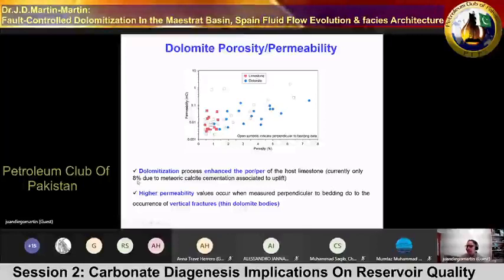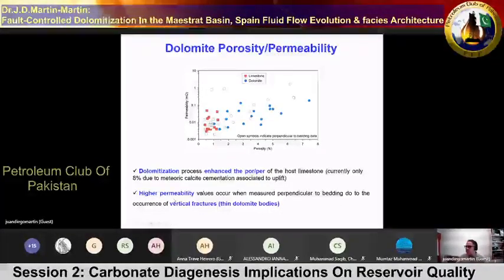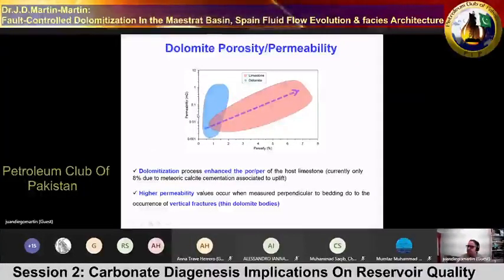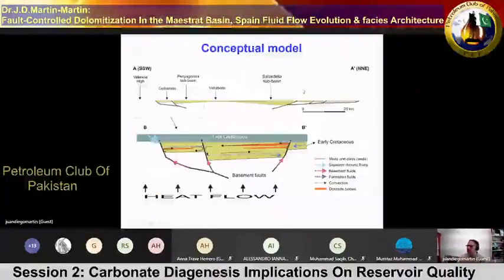Porosity is currently only a maximum of 8%, and this is due to the meteoric calcite cementation associated with uplift, something that we were showing before. And we have higher permeability values in those samples measured perpendicular to bedding due to the occurrence of vertical fractures. This occurs in thin dolomite bodies. Anyway, these are the trends. The blue is the limestone, and in red the dolostones, and this is the trend of the increasing porosity.